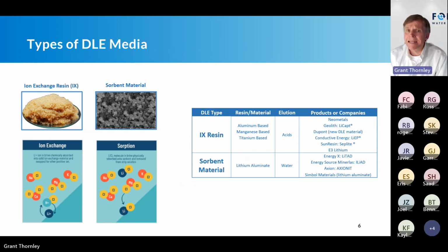Getting into the types of DLE media, with ion exchange there's a functional group, and the lithium will be absorbed into the ion exchange media. Then there are absorption materials, where the lithium chloride will be absorbed onto the surface of the medium. So ion exchange is into, absorption materials are onto. The difference between the two is basically their functional or material groups. You'll see aluminum-based, manganese-based, titanium-based. It all depends on what type of contaminants you have and what you're trying to achieve. One may be better than the others.